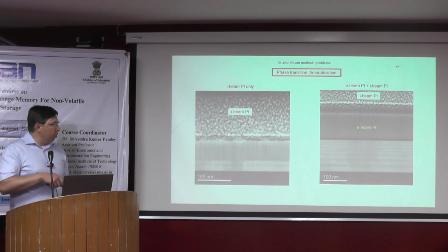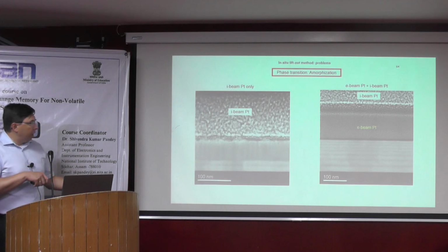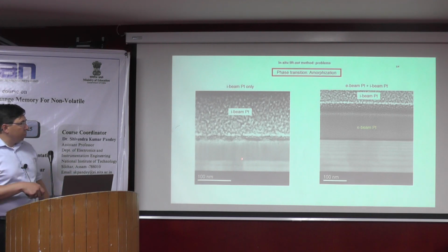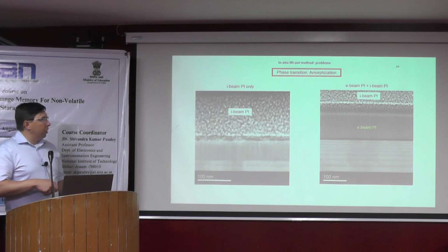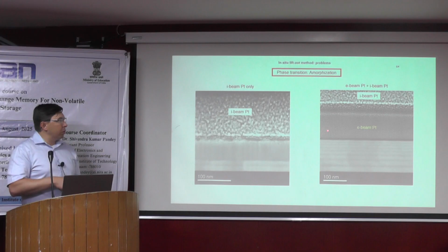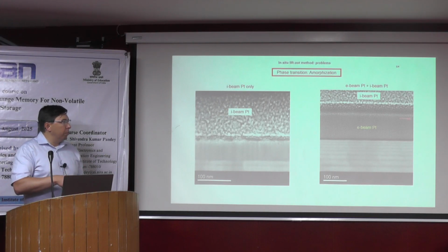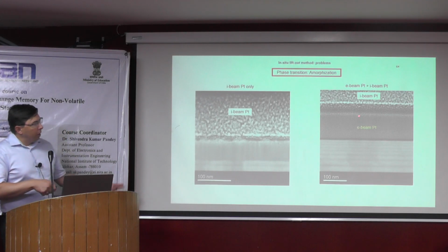So we think that the ion beam interaction just kicks the atoms in the lattice away a little bit, and then the system goes amorphous. So you should also be aware of this, and please always use extra layers, like deposited directly in the system or externally.